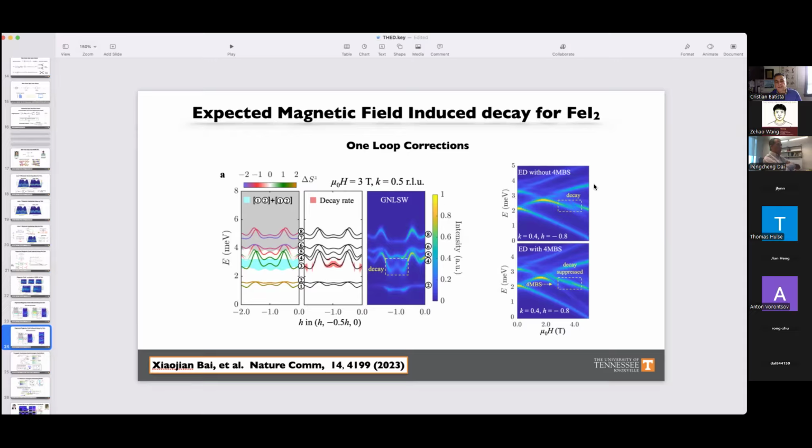However, we can capture it with this exact diagonalization in the truncated Hilbert space. And what happens precisely is the moment you turn on the vertex that leads to the formation of the four-magnon bound state, you see that the decay that you used to have before turning on that attraction now becomes much weaker, right? So essentially, part of the continuum goes into the formation of a four-magnon bound state, and then you see a weaker decay. So all this story to tell you that you need non-perturbative approaches in order to capture effects caused by the formation of bound states or resonances.